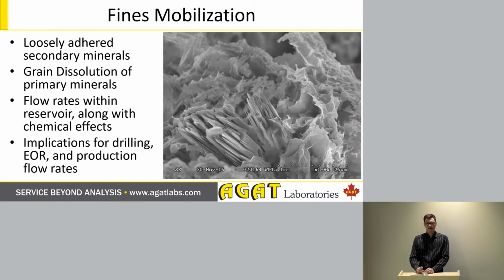This is an example of grain dissolution. What we have here is a plagioclase that has had grain dissolution along the length of intersections within the cleavage of the plagioclase crystal, and that has left these shard-like projections sticking up into the pore space. These shards can actually dislodge themselves and start flowing, but also there's a lot of implications for the ions that have been released into the fluids surrounding all of the other minerals, and so we now have a lot of different fluids present that may react.